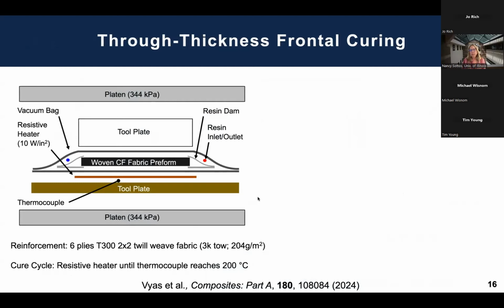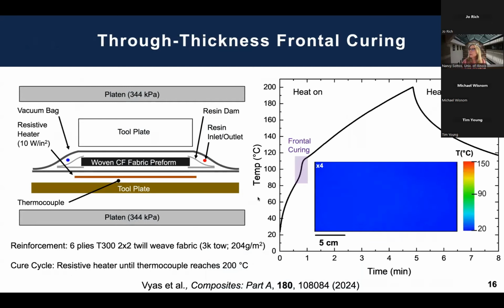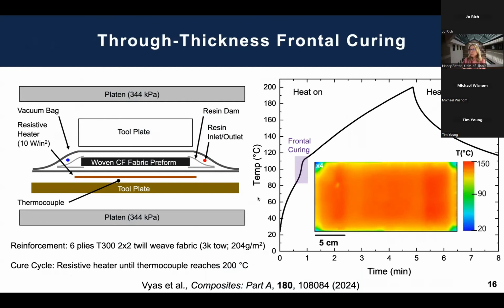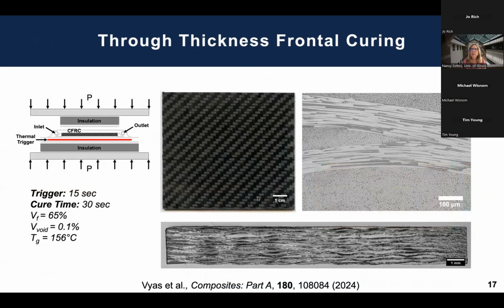Since that time, it isn't really practical to move the front along the panel. You can actually do this even more quickly if you do a through thickness cure, so the heat comes up through the bottom just through the thickness. And if you add a little more heat, so there's a little more energy in, as I show here, you can cure the composite through the thickness. You see the IR image of just the wave coming through. And this can produce actually very nice composites. We can get the Tgs well up over 150 to 160 degrees C.